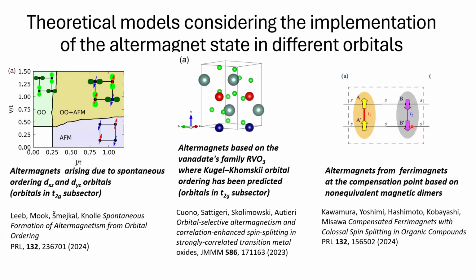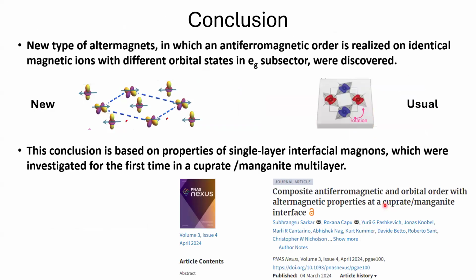And if this ferrimagnet is based on non-equivalent magnetic dimers or non-equivalent ions, then, as shown in this paper, we again get altermagnet properties. So now my conclusion is that we uncover a new type of altermagnet in which an antiferromagnetic order is realized on identical magnetic ions with different orbital states in the eg subsector.